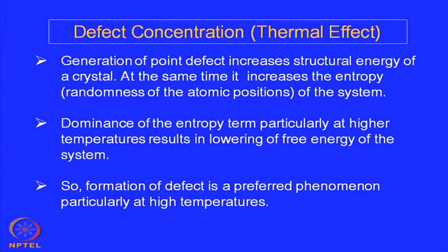But there is another very important parameter which also has a great influence on the defect concentration, that is the thermal effect, the temperature effect, and that is what is written here. The generation of point defects increases the structural energy of a crystal, and at the same time it increases the entropy, the randomness of the atomic positions of the system. Dominance of the entropy term, particularly at higher temperature, results in lowering of the free energy of the system. So, formation of defects is a preferred phenomenon, particularly at high temperature.